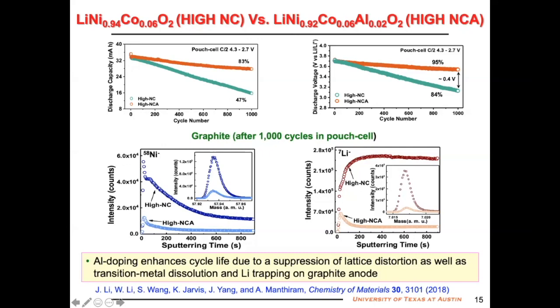Why? If you do not have much aluminum or do not have any aluminum, you have more nickel crossover to the graphite compared to the sample which has 2% aluminum. And that also leads to more trapping of active lithium on the anode compared to the material that has 2% aluminum. So aluminum, magnesium, and even boron or other dopants do a lot of magic to make a big difference in this.